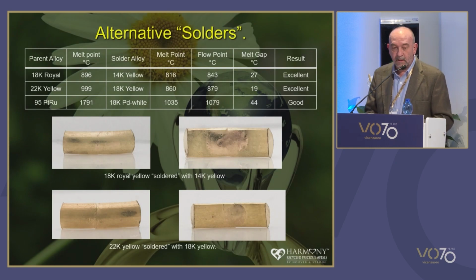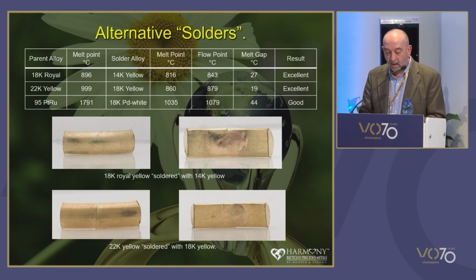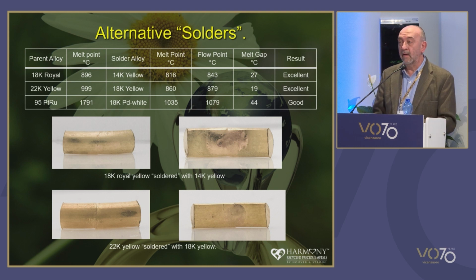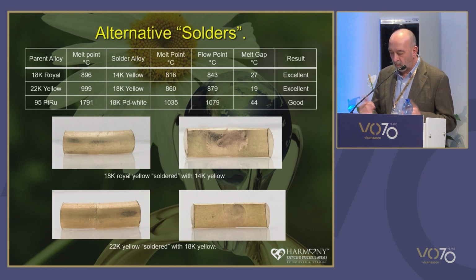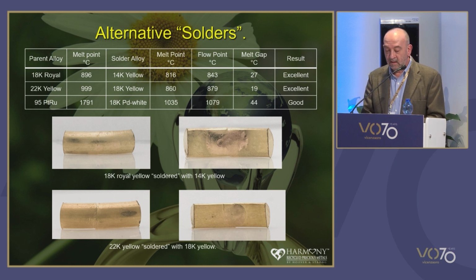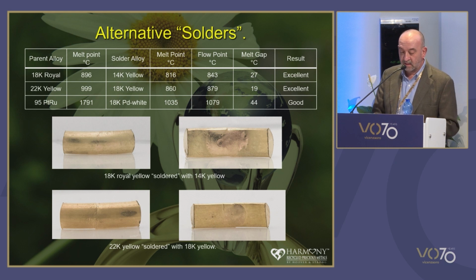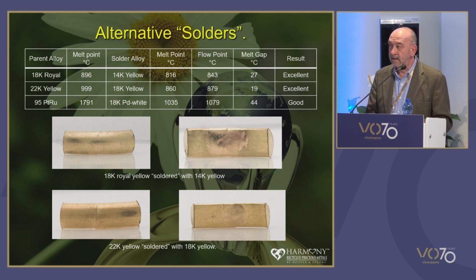So we used straight 14 karat yellow gold to join 18 karat yellow gold. So this is just normal 14 karat sheet, 14 karat wire, and we decided to use it as a solder, and it worked very, very successfully. You could arguably say that's one of the best results in the entire test, even better than the solders.